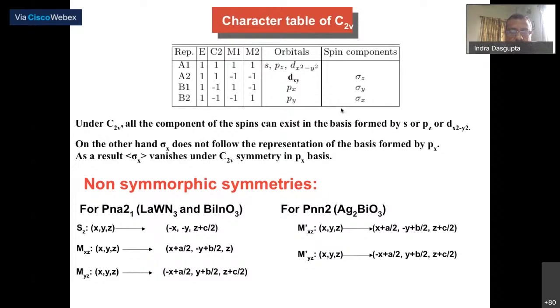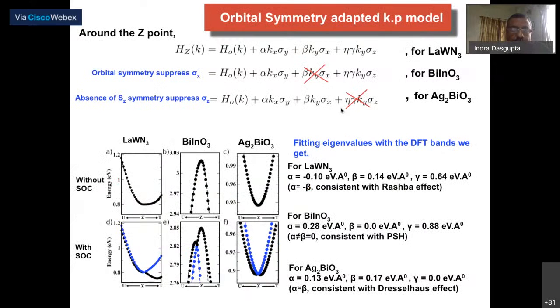But as soon as you have a px orbital, it has no room for the sigma z and sigma x components. So one has to take this into account while modeling it, and this is precisely what we have done. When we were studying LaWN3, the symmetry allowed sigma x, sigma y, and sigma z components. But when we looked at BiInO3, since the orbital character happened to be px, the sigma x component was no longer allowed. And for Ag2BiO3, the symmorphic symmetry operation was such that the sigma z component was not allowed.